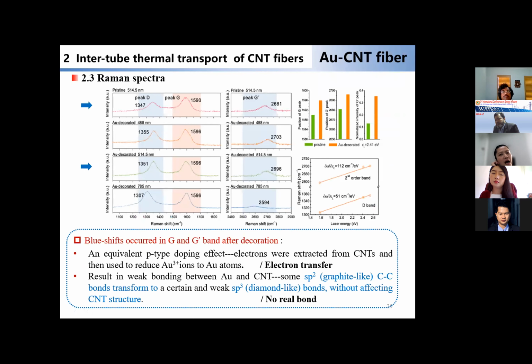We can also see an obvious blue shift after gold nanoparticle decoration. Comparing these two pictures, they occur equivalently, which means an equivalent p-type doping effect, that is, electrons were ejected from tubes and then used to reduce gold ions to gold atoms, that is electron transfer. And this results in weak bonding between gold and tubes.